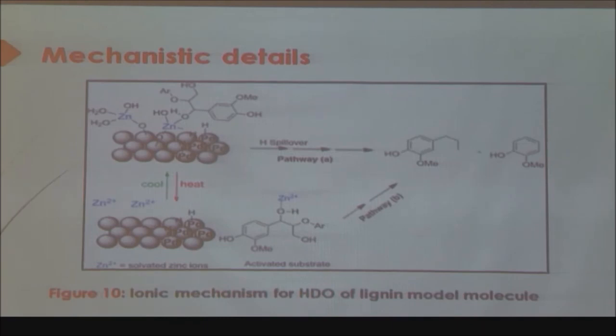So here we say that if you have ions, for example, a metal ion, that metal ion can coordinate to these groups and these somehow can split. So when an ion is coordinating with the ether bond, will it promote homolytic or heterolytic cleavage? Students, guess. Zinc ion in the positive state, if it is coordinating with the ether bond, will it promote homolytic or heterolytic cleavage? Any guess? Yes, because it is an ion, it will try to take both the electrons and probably promote the heterolytic cleavage. So heterolytic cleavage will initiate the formation of ions and not the free radical intermediate.